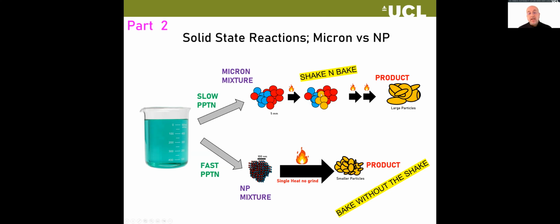Normally, the first time you heat it, the reaction happens at the interface, and you've still got a lot of unreacted material, which is not fully reacted. So you then do a grinding step, and then you do another few heating and grinding steps, and eventually you get to the product. And the product might have some large particles because you heated it many times and ground it many times. Our philosophy of bottom up is to say, okay, these two elements, the red and the blue, if we can make them in an intimate mixture, either a solid solution or